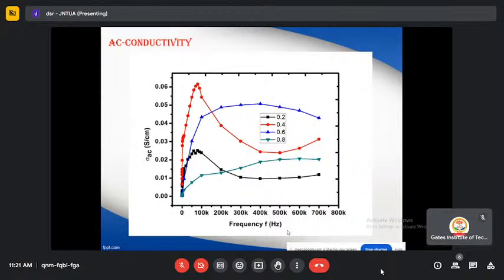For x equal to 0.6 and 0.8 compositions, they exhibited an exponential increase up to 399 kilohertz. Above the resonance frequency of 399 kilohertz, a gentle decay was noticed for both the 0.6 and 0.8 compositions. But the 0.4 sample exhibited higher electrical conductivity than all the remaining samples.